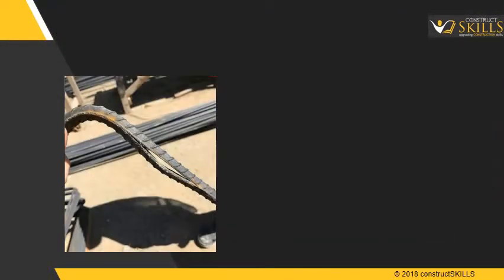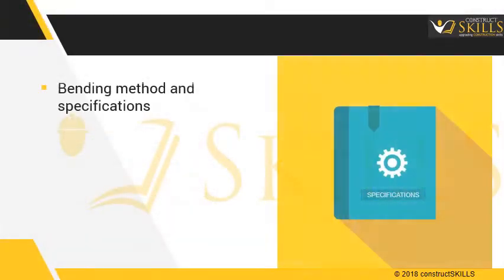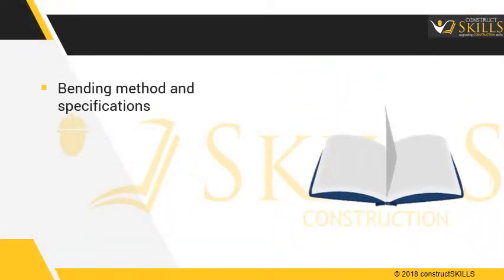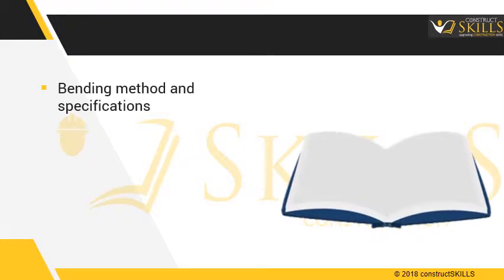It is a commonly known fact that because of bad quality of reinforcement, it cracks. This is usually the case because the carbon content in the bar is high, making it brittle. However, in this case, the bending method and specifications were not followed.